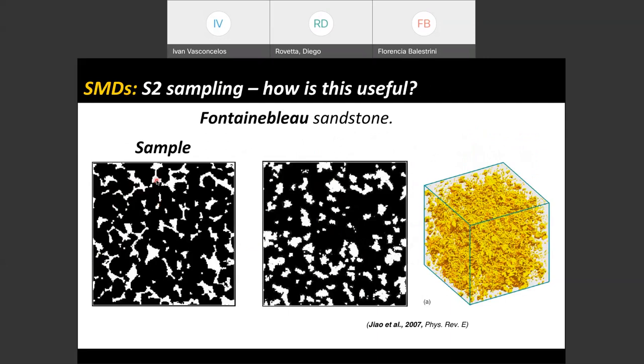We can take this sample, we can extract the two-point correlation function. Then we solve an inverse problem where we say, give me now a pixelized version of a material that fits the two-point correlation function. So you solve an optimization problem and you get what is called a reconstruction. And here you see a reconstructed version, a new sample of the material that is statistically corresponding to the same sample that you originally had. You see it in 2D, you see it in 3D. Now, arguably, this looks realistic, but whether this is a good reconstruction or not depends on what you want to do with this reconstruction. Feel free to ask me questions about that at the end.